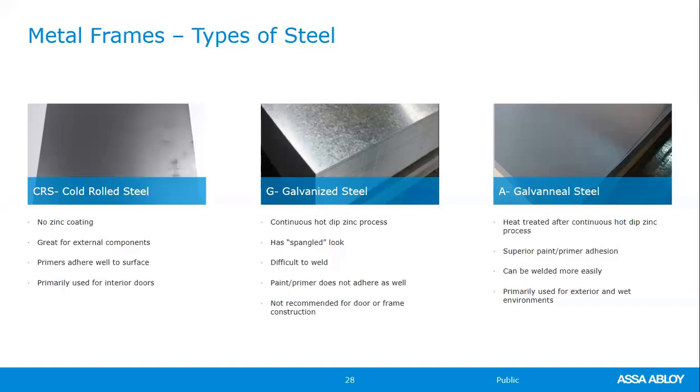The next one is your G designated galvanized material. This is what we call the hot dipped process. Basically, with the galvanized material, they dip the steel in zinc, so it covers both sides of the steel, and they bring it out. So it's a continuous hot dip process, and then they let it dry. With that, you'll get this high spangled look, like ductwork, garbage can types of steel, very spangled looking. With that process though, the difficulty comes in being able to weld that material. Paint and primer don't adhere to it as well as they would with cold rolled or CRS material. Even though our factories have G material inventory, if the job calls for it, just be aware that galvanized material is going to be a lot more difficult to modify and have paint adhere to it.